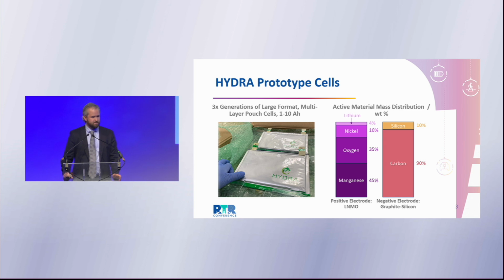LNMO can operate at high voltages of like 4.8, 4.9 volts, compared with NMC, which operates at 4.2. On the other hand, we have the active material in the negative electrode, which is a mix of carbon in the form of graphite and silicon. And for the non-battery people in the audience, graphite is a very stable material, but not so high energy. On the other hand, silicon is extremely high energy, but not very stable. So by creating a kind of blend between these two things, we're able to get benefits from both and try to improve the overall performance.